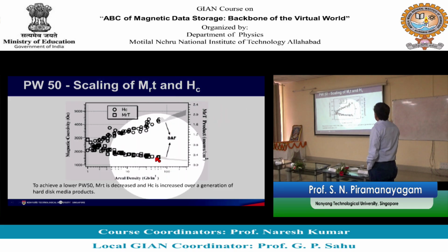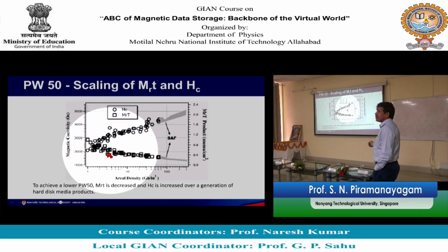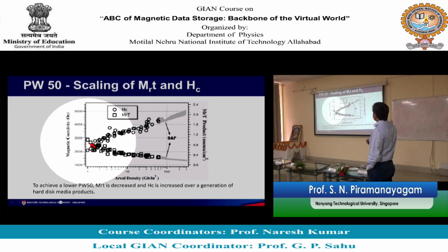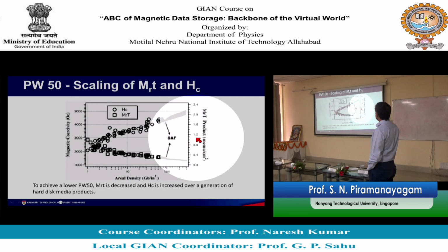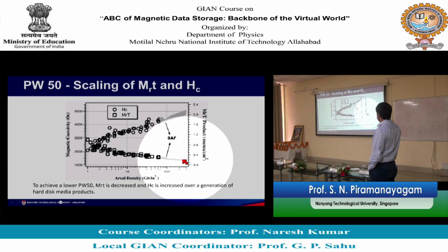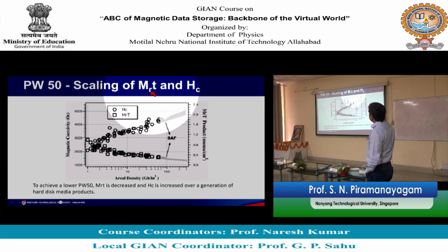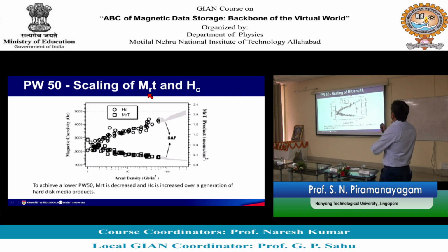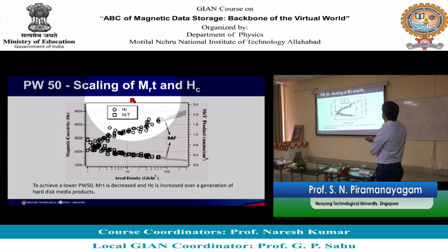If you look at this picture, the circle is coercivity. So, coercivity has been increasing. When you go from poorer density to better areal density, the coercivity kept increasing and the MRT was dropping, right. So, from say 1.2 memu per centimeter square, the MRT is reduced to like 0.3, 0.4. Typically people reduce the MRT by reducing the thickness. So, you want to make the film not too thick. So, basically this is reduction in the thickness of the films.